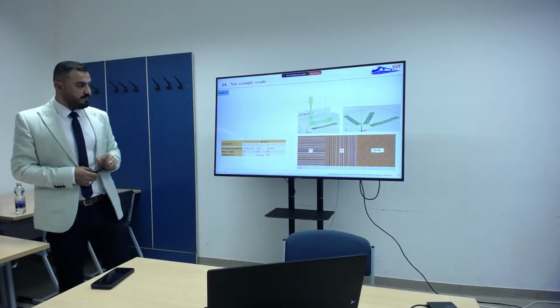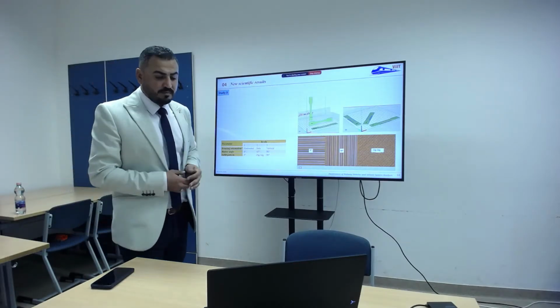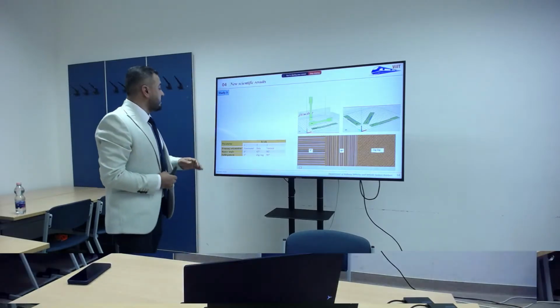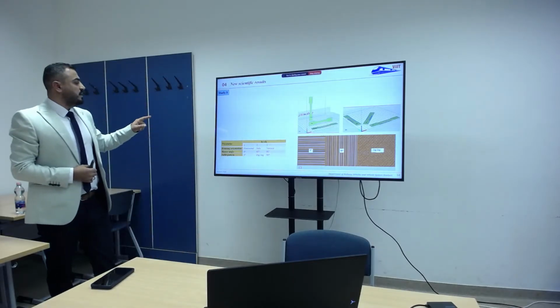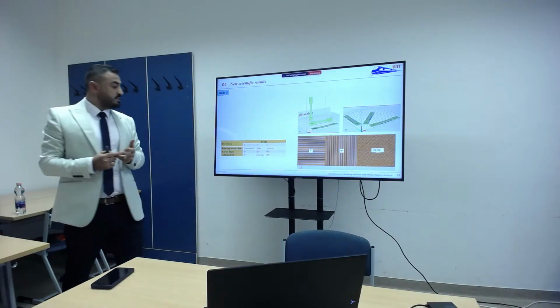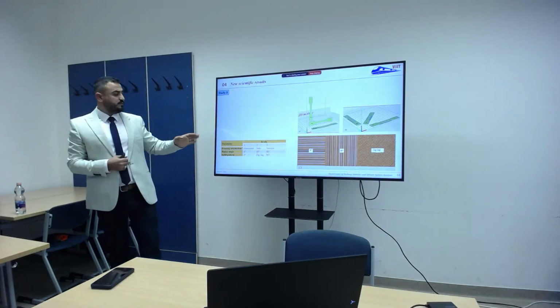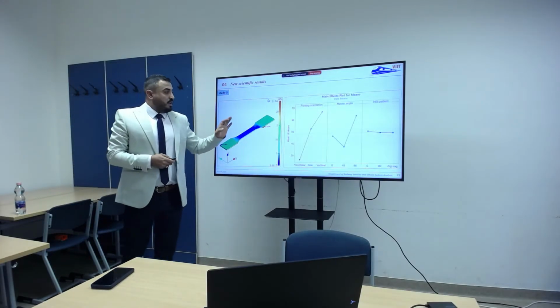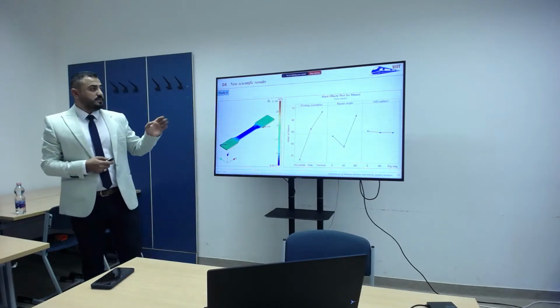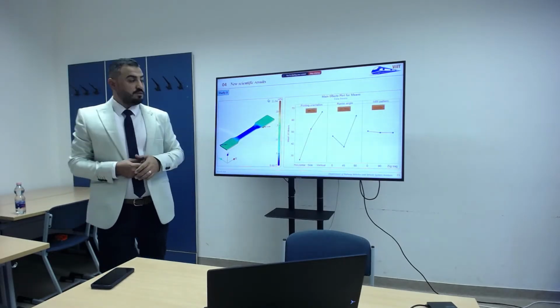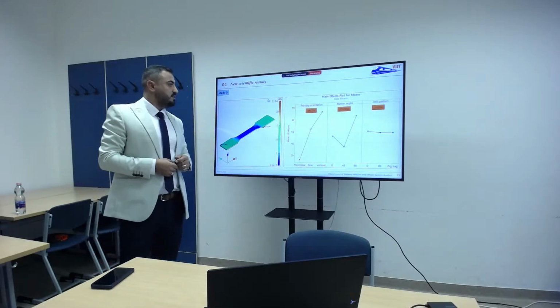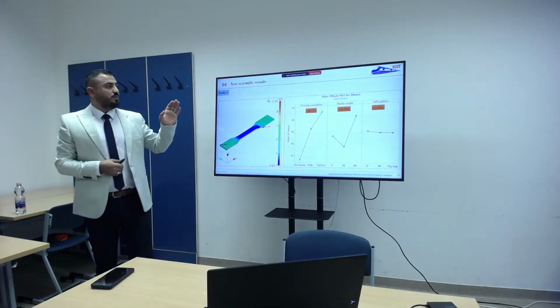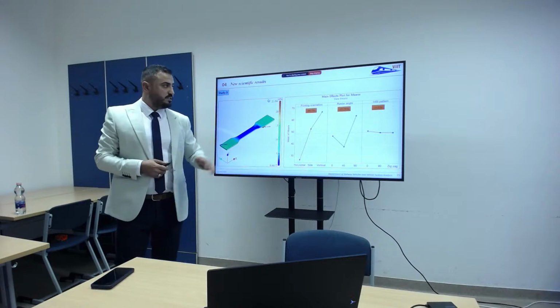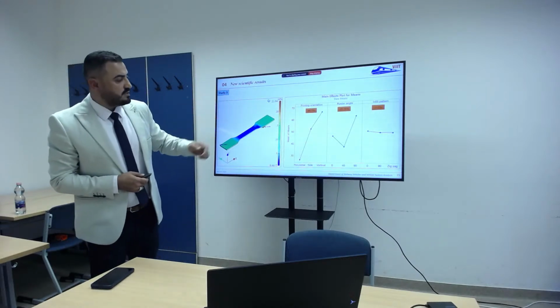For the third study, I investigated the structural parameters: the printing orientation, raster angle, and infill pattern, with 3 different levels. And the results showed that the printing orientation was also the most dominant factor, with about 66.7%, while the raster angle was 25%, and the infill pattern also does not have any impact.